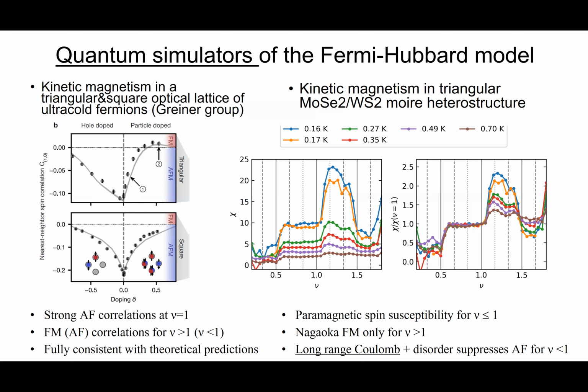So I have one very quick naive question. Is it always true that excitons are a good spin sensor, in the sense that what about depolarization in this kind of mechanism? Yes, very good question. What happens around here is that indeed the excitons destroy the magnetic state. That's at least what we believe is happening, because we can see that this depolarization effect associated with light sensitivity is very different depending on light intensity.